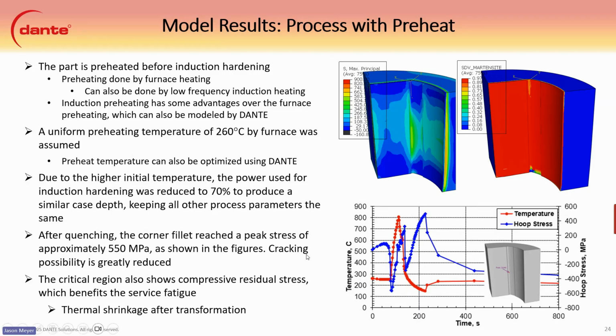After quenching, the corner fillet reached a peak stress of probably about 550 MPa, as shown in the figures here. You can see the hoop stress again is on the secondary, and the cracking possibility is greatly reduced by this magnitude being much lower. Let's start here with the temperature. It's about 260 degrees to start, and then we heat up to about 800 degrees or so in the corner there, and drop it down to room temperature with the quench.